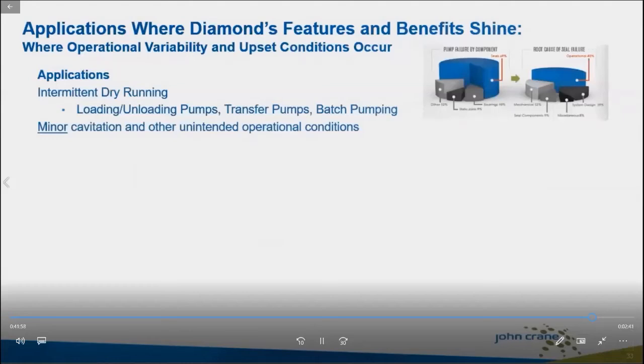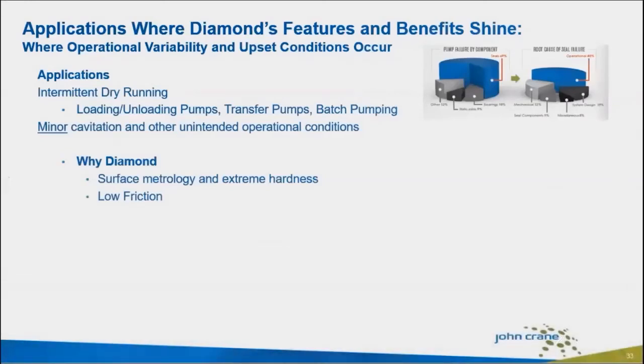So why diamond here? This is due to the design of the surface metrology and the extreme hardness of diamond. The texture and the hardness of diamond reduces seal face damage during these extreme conditions, and depending on the excursion, the diamond treated seal may continue to be fully functional, where a non-diamond treated seal might have catastrophic damage and would require a repair or replacement.